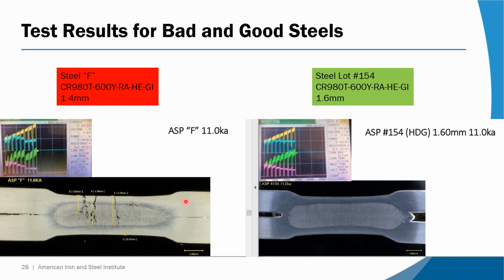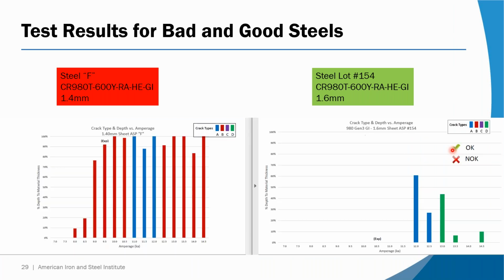The one on the right is just still doing fine, no cracks. So this test continues. We don't stop at 11 kiloamps, we start at 7 kiloamps and go up to 14.5. So every position on this x-axis represents a weld that was made at a particular current, as indicated. And if there's a crack, there'll be a bar on here indicating that there's a crack.